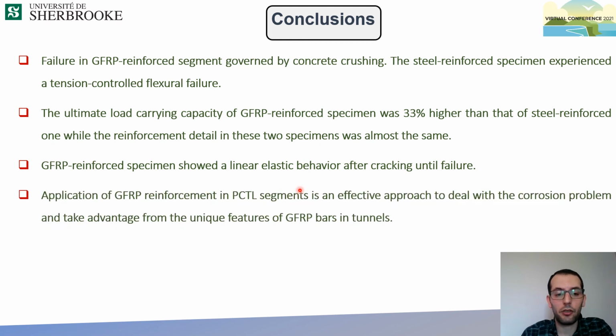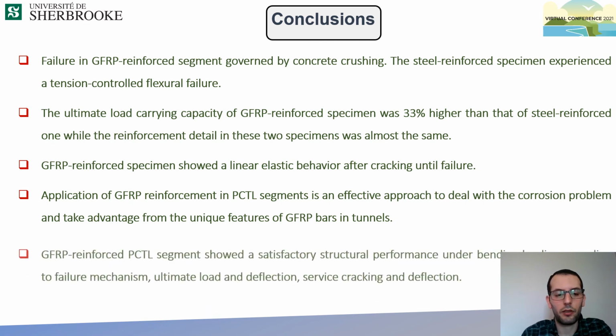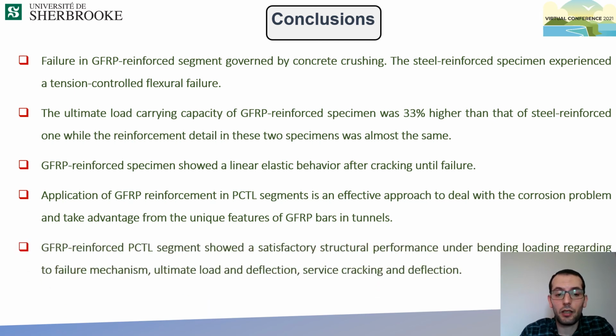We can say that application of GFRP reinforcement in PCTL segments is an effective approach to deal with the corrosion problem and to take advantage of the unique features of GFRP bars in tunnels. And GFRP reinforced PCTL segments showed a satisfactory structural performance under bending load regarding failure mechanism, ultimate load and deflection, service cracking, and deflection.